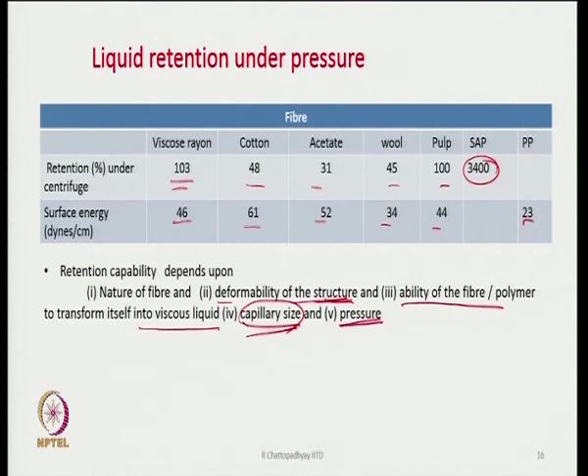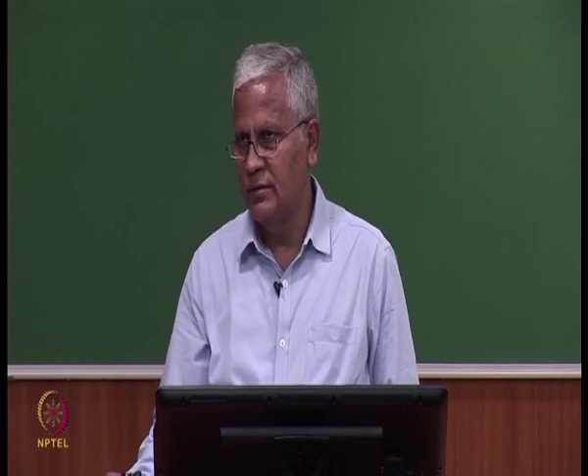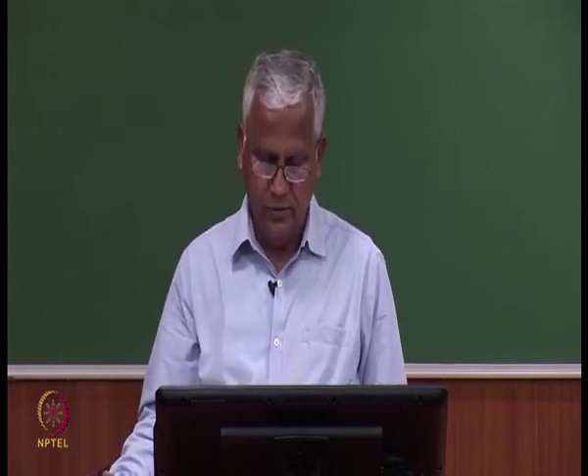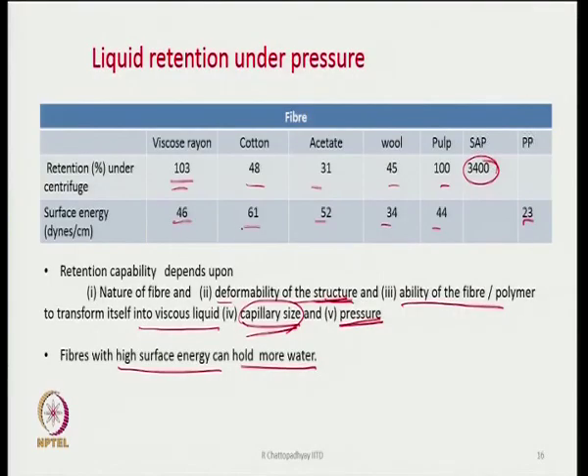Then comes the external pressure that we apply. If the pressure is less, more liquid will be retained. If the pressure is more, less liquid will be retained. That is how liquid retention will change. And fibers with high surface energy can hold more water. They will not allow the water to move out from the capillaries so easily. They will create resistance to the movement of the liquid flow. So that way, cotton has an advantage. Suppose we use polypropylene. Polypropylene non-woven can absorb some liquid, but if we put a little pressure, most of the liquid will flow away, like a sponge. Sponges themselves can absorb, but after absorption, if you put a little bit of pressure, most of the liquid moves away from the sponge.